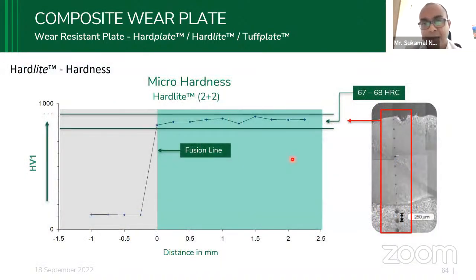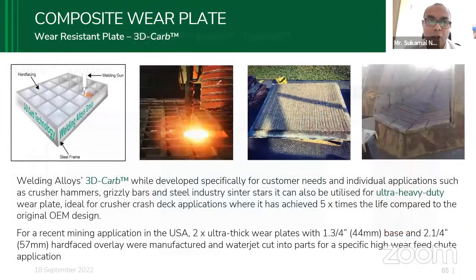And it's basically complex carbides. So the micro hardness, how it goes: we think it's soft, but the moment it goes up to the fusion line, you can see it has drastically increased the hardness, like 67 to 68 HRC. So you can see that any kind of abrasion, impact, erosion, it can very nicely protect at the surface level. So yeah, exactly, this is how it goes. This is the manufacturing technique, how you put it, and this is the final product, and it goes onto the component.